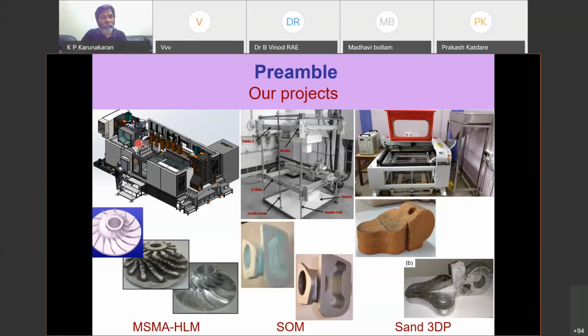You can have a face milling cutter on the main spindle. You can have a preheating system. We have developed an induction based preheating system that can be on the other side of it. And in the remaining area, we could have different cladding heads: MIG cladding head, TIG cladding head, laser cladding head. We can put a camera and inspect it. After the face milling, we can inspect the layer and see whether the layer has any defects. If it has defects, then we can face mill again and repeat it.